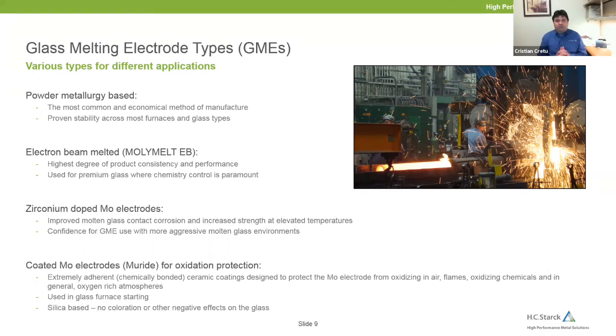As a result, first of all, you'll get a fully solid electrode, right? There will be no voids. The amount of impurities is greatly reduced. The typical electrode is 99.95, and it has a certain chemistry, but in the process of electron beam melting, most contamination is eliminated or dramatically reduced, right? So this is a different type of electrode. It's typically more expensive because this is not a cheap process to implement, but it does generate extremely high quality product.